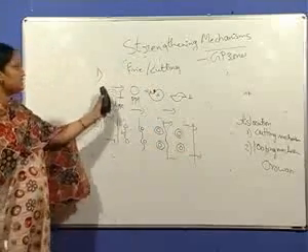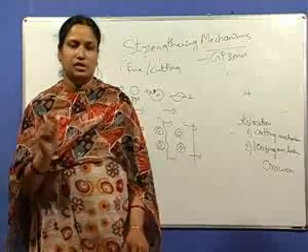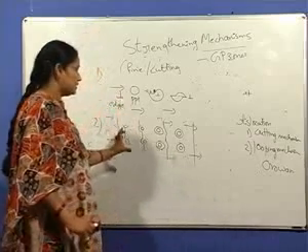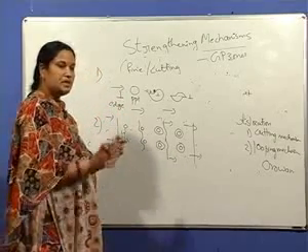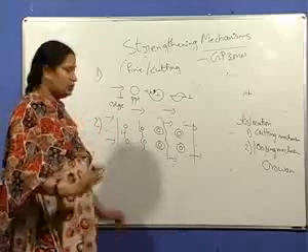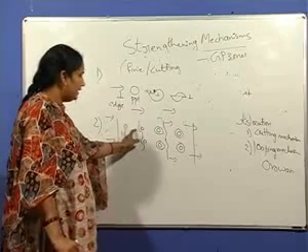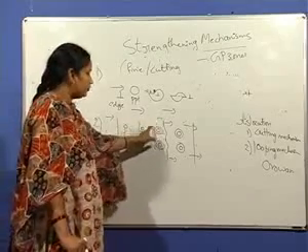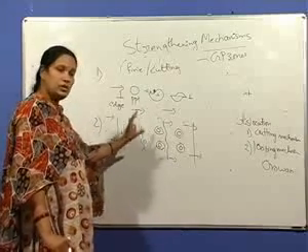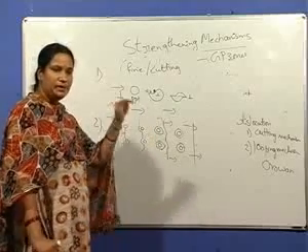So the first one is the cutting mechanism. When the precipitates are very fine, they are shearable by the dislocations. When the precipitates are coarser, besides the stress required to bypass, the dislocation has to bend around the precipitates and form loops around them. It has to bypass the obstacles, the precipitate particles, by forming loops.